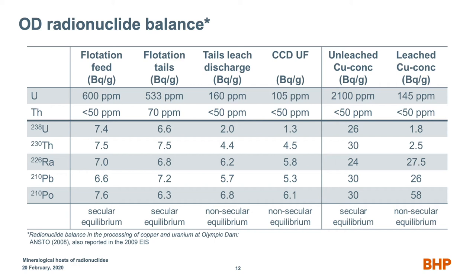But the big thing we see is we had something that started off with roughly 30 becquerels per gram, and we dropped it down pretty low. The radium, lead-210, and polonium-210, particularly the lead-210 and polonium-210, haven't changed, but polonium-210 we've enhanced a little bit, and that's because we do a dust bleed from our smelter. But the important thing is they're not being touched, or apparently not being touched, at the sample scale by concentrate leach. So we're dissolving out the uranium, we're getting rid of the thorium, but the things that are annoying, lead-210 and polonium-210, they hang around. So why aren't we dissolving them? We're dissolving the mineral that was the original host of these, but they're still hanging around. Why?